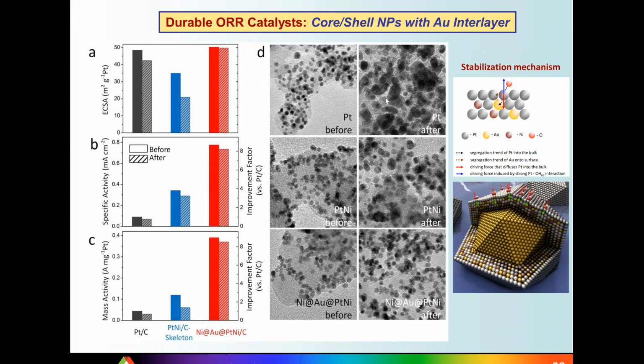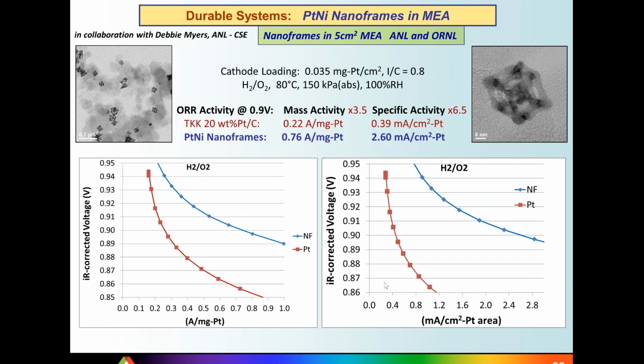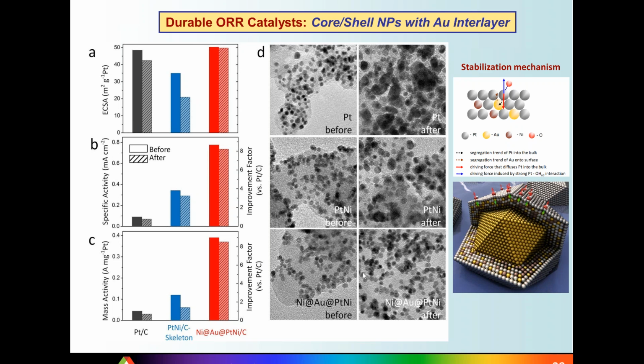Those are typical platinum carbon catalysts before and after, and also platinum nickel commercially available before and after. And this is our core interlayer shell, so absolutely no change in surface morphology, no change in performance. So indeed, placing gold in such a way can address the durability issue very effectively. So that was one way how one can improve not only activity but durability as well. The other, as I mentioned, was that multi-layered platinum skin.